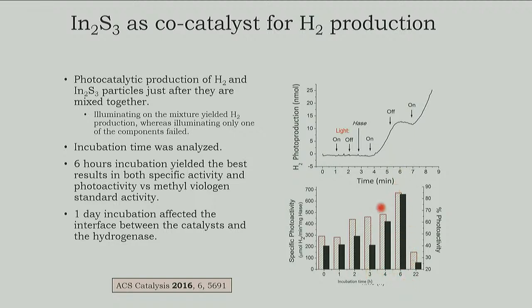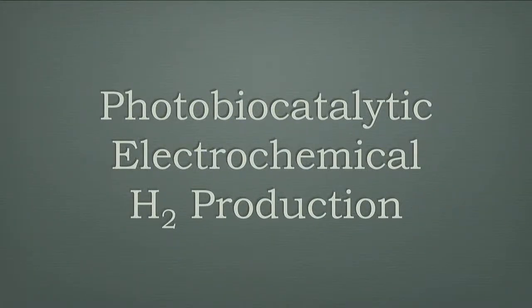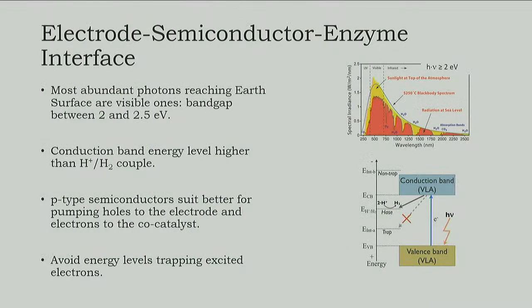And also it's very interesting that the photoactivity corresponds to 90% of the photoproduction of the hydrogen produced here. So it's a more efficient time, the optimized incubation time here. But we had a problem because as indium sulfide is an N-type semiconductor, when we put this on an electrode, it didn't work because the electron flux, the excited electron flux, was going the other way. This is why it worked with laccase for oxidation, but not for hydrogen production.